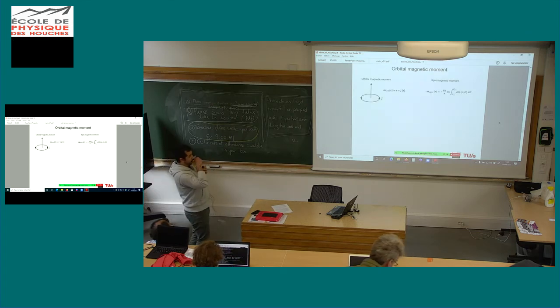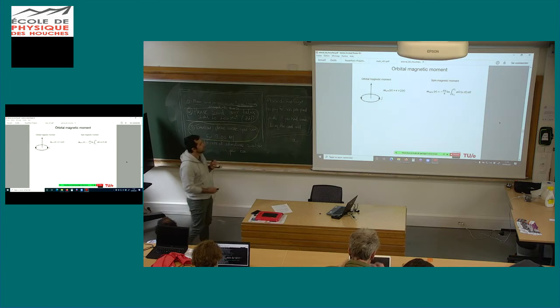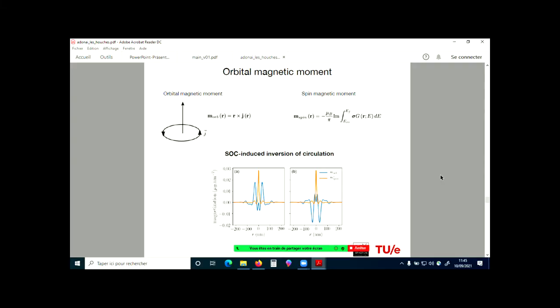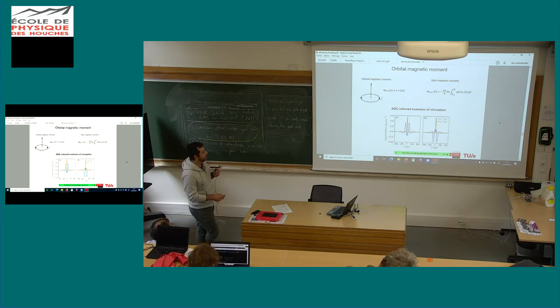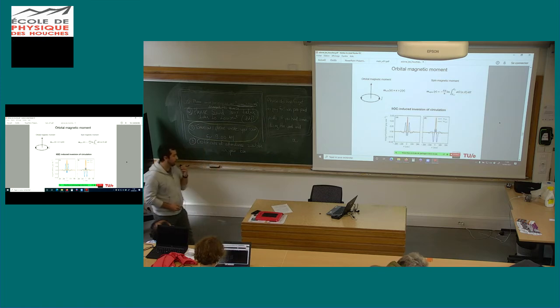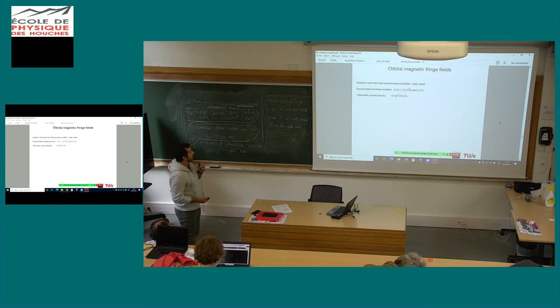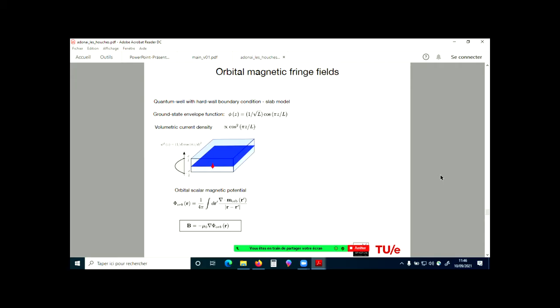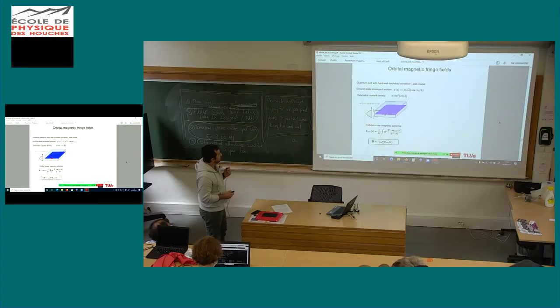And I come to the orbital magnetic moment. So here I'm comparing both the contribution from these currents and the spin, that's the type of field. As I mentioned before, the spin-orbit coupling induces inversion of circulation. So here in the orange curve is the spin magnetization close to the impurity, impurity 0. And we tune the alpha by electric field. The orbital magnetization basically changes completely around alpha equals beta. And just to put here, these orbital magnetizations can be probed by fringe fields, so these magnetic fields outside the quantum well.